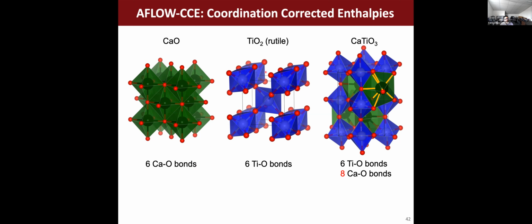If we have a rutile phase of titanium oxide, we have a similar scenario. We have the titanium in the middle, and six oxygens coordinated around it. If we put these together and make calcium titanium oxide, we still have coordination 6 for the titanium, but we no longer have 6 for the calcium. We have 8. So if I had a generic correction which just looked at calcium and oxygen, the relative composition, it should not be the same for this composition because we have a different coordination for the calcium. So we want a correction scheme which is dependent on the exact coordination of how it exists in the material, which really comes down to oxidation states.